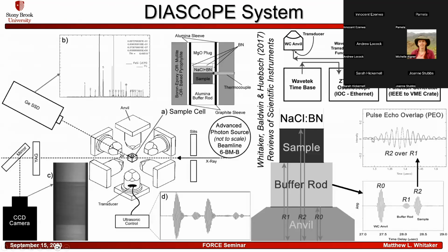At the time, multi-anvil based ultrasonic systems in the US took about 150 to 200 seconds to collect their 1024 waveform acquisitions. SPring-8 in Japan at the time took 45 to 60 seconds to collect this. These relatively slow collection speeds limited the types of experiments that we could do and the types of measurements that we could make. They also relied on a single detector, which gave us no information on potential differential stresses. So we came up with the DIASCoPE system.